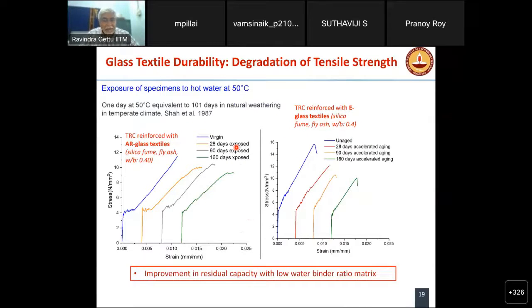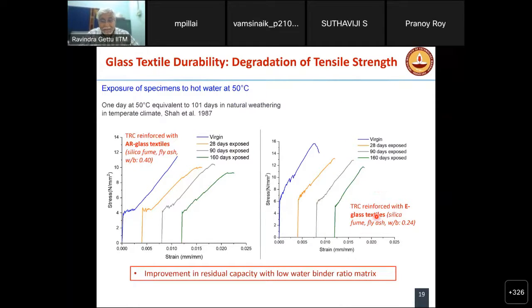And so we want to have a behavior similar to AR glass in the E-glass also. So we have some loss in behavior, but we are trying to change the binder. So this is a more efficient binder, lower water binder ratio with fly ash, and we see that already we are approaching the behavior in AR glass, though we have to improve more things. So basically what we are doing is taking E-glass, which is a cheaper glass, and modifying the binder so that we can get better behavior and less durability problem. So this is what a major part of our research is focusing on.